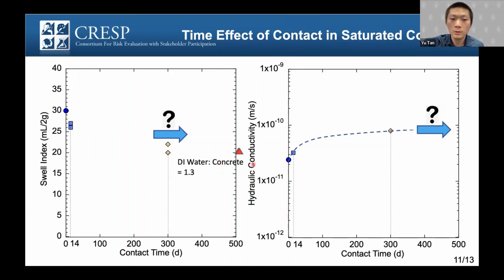This is what I did in the last weeks. I just mixed the water and concrete at a 1:3 ratio and shook it and finally filtered the water to get the water to represent the pure water in concrete, and ran the swell index test with the fresh bentonite. And we found that the swell index in the kind of pure water in concrete is still comparable with the swell index after 300 days interaction in the column test. It means that in the saturated condition, the interaction between the concrete and the GCL may have reached equilibrium. So if we run the column test for a longer time, we may get a flat trend at the end. So our results are favorable, that the GCL works pretty well based on our results for now.